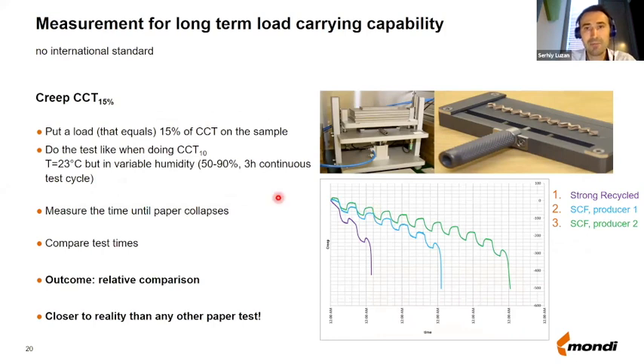Here you have an example of CCT15 test. As you remember, the difference between CCT10 and CCT15 is that CCT15 is conducted at changing humidity conditions. So you change the humidity from 50 to 90, from 90 to 50, and so on, in a cyclic manner with a step of 3 hours. And then you measure the time until paper is collapsing.